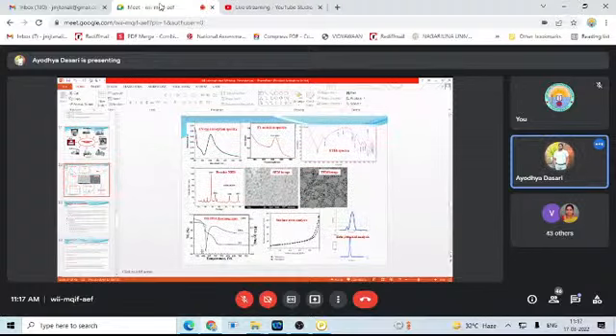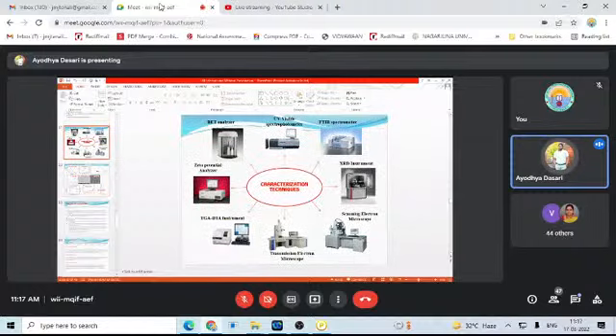This is the example. The TGA applied up to 750 degrees centigrade gradually decreases from 100% to 70%, meaning 30% degradation, so it is thermally unstable at 750 degrees centigrade. It is observed by the thermogravimetric analysis. And from DTA, differential thermal analysis, we can find exothermic or endothermic reactions. So the major purpose of the TGA DTA instrument is thermal stability and exothermic or endothermic reactions of the synthesized nanomaterials.